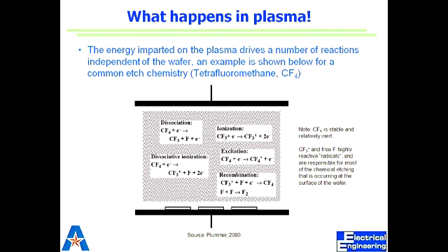In addition to that, nature of the surface means how selective, how reactive, how fast it reacts. Yes, removal of the residues, that is one part of the loading effect, which I will discuss. So out of the parameters, pressure is one. In addition, the surface temperature, nature of the surface, and geometrical aspect of the surface. If it's a very deep trench, of course the etch rate would be smaller, but if the area exposed is high and the source of etchant is unlimited.